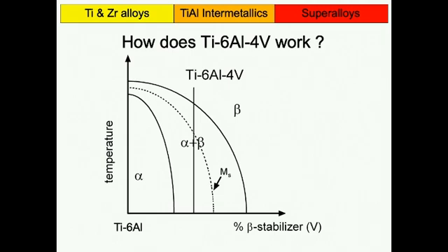And then you can see here there's a dashed line, and this is a line indicating the martensite start temperature. If you're on the left hand side of that dashed line, when you cool or quench your material, you get the martensite phase transformation. You cannot retain a lot of beta phase during quenching. It just transforms martensitically.